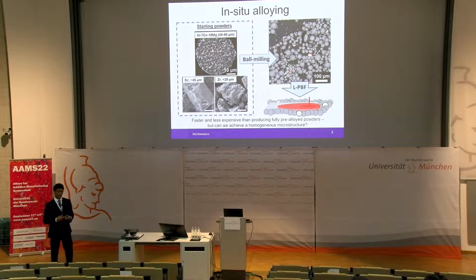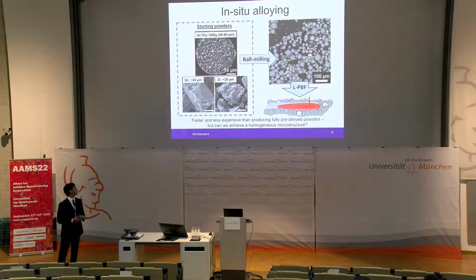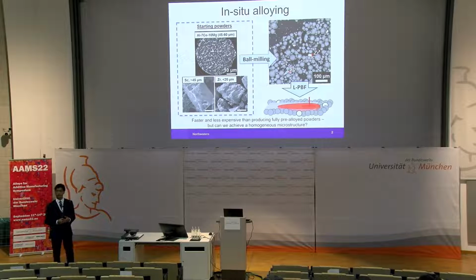Now, the alloy today is manufactured not by using fully pre-alloyed powders, but by instead using this technique of in-situ alloying, which some other researchers at this conference are presenting on. So the idea is that we mix these aluminum-cerium-10-magnesium powders and add to it elemental scandium and zirconium powders. We gently ball mill it to achieve a homogeneous distribution, and alloying takes place during the laser powder bed fusion process itself.